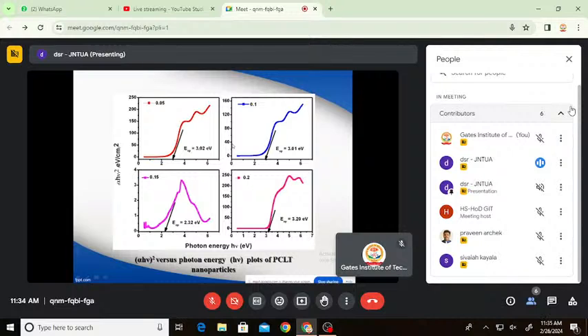It indicated that the smaller lanthanum content was not capable of establishing a sufficient modification in the energy gap. But for y equal to 0.15 content, it exhibited a narrow optical band gap of almost 2.32 electron volts. In addition, at y equal to 0.2, a wide band gap of almost 3.2 electron volts is observed.